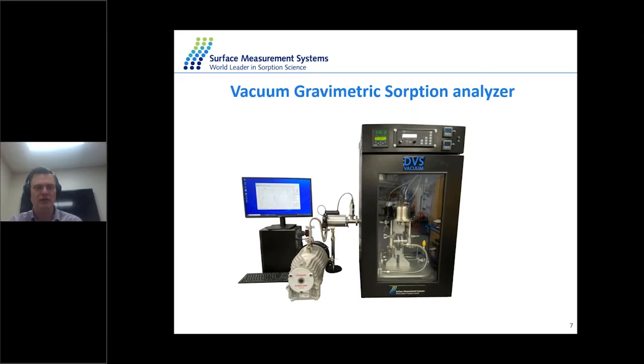So here's the picture of a DVS vacuum analyzer. DVS vacuum system is a gravimetric vapor sorption analyzer. So it comes with a PC, a set of dry pump and molecular pump, and the temperature enclosure. We call it incubator. This is very important because your sample, baratrons, mass flow controllers, everything is inside this temperature control enclosure, operating in the range 10 to 70. So what it means in this temperature range, I can generate vapors up to 90%. We can work with most of the molecules.